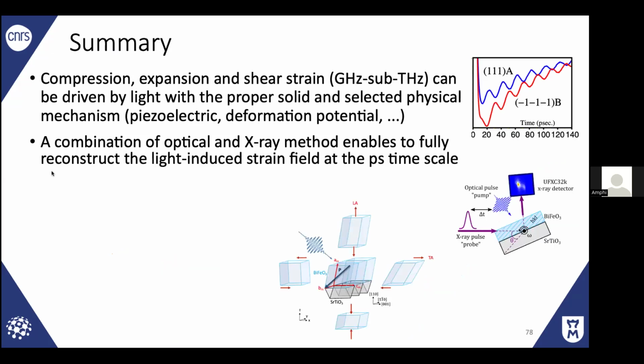So what I showed you is that finally, with light, we can induce compression, expansion, or shear strain. If you understand properly the electron, because in all situations I discussed, we have a creation of electron-hole pairs. So this electron-hole pair induces deformation potential stress, or can screen an electric field, or can induce a Dember field. Each time we have a creation of electron-hole pairs. But by selecting the material and the symmetry, you can really control the kind of the different strain in the solid.